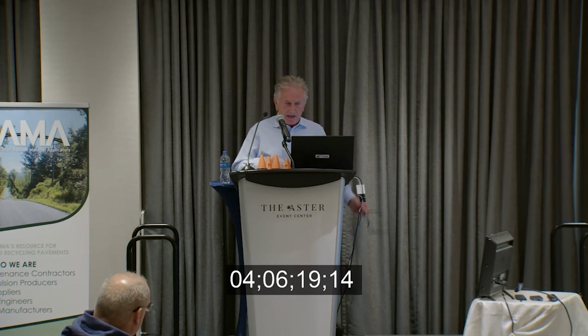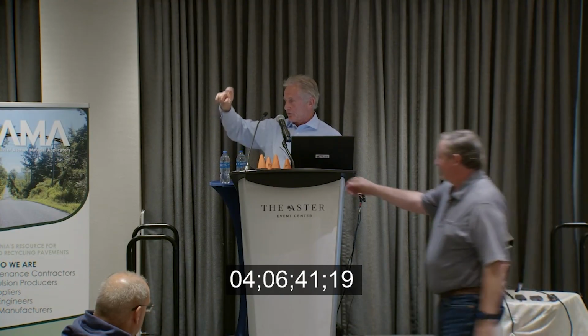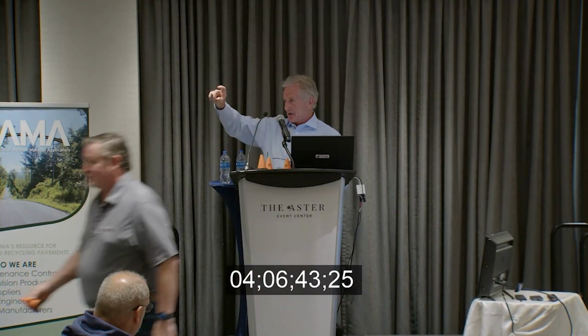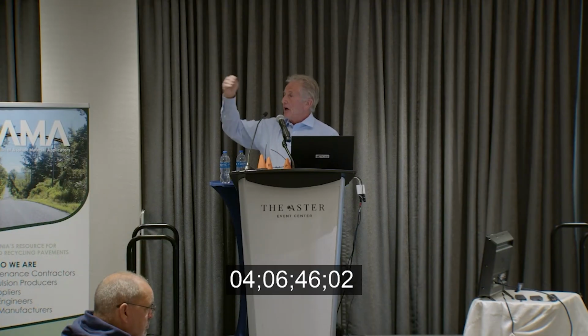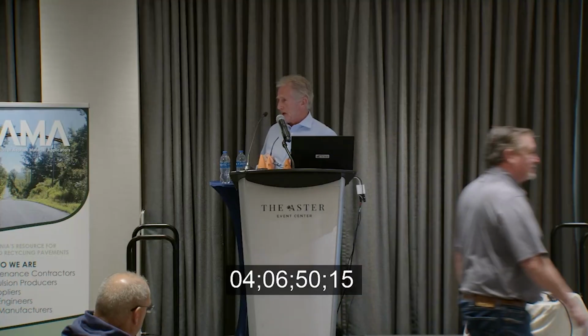So we're going to go on to full depth. Yes, I'm sorry. During curing time, would you let traffic drive? Traffic's going to drive on the mat, probably within 2 hours of that mat being laid, whether you have the Portland cement in there or not. The traffic's on it. It's a top-down cure. That top is curing 2 inches at least, okay? 2 inches at least, and we're going to allow traffic to run on it. We'll put a prime coat down, but traffic can run on it right away.